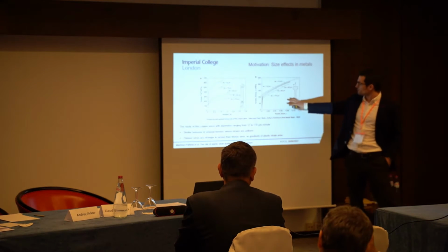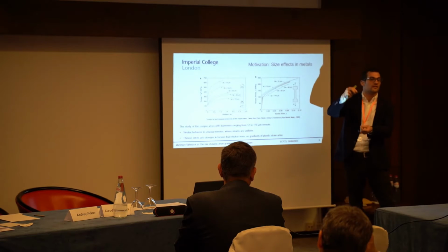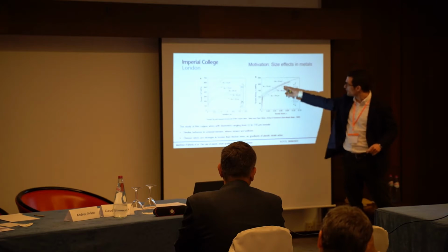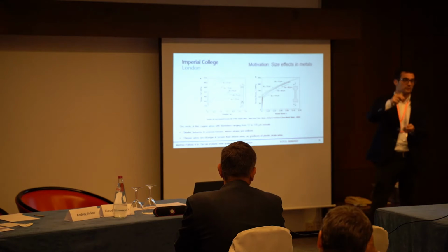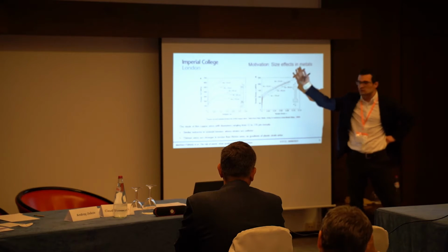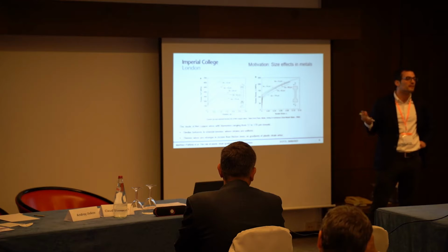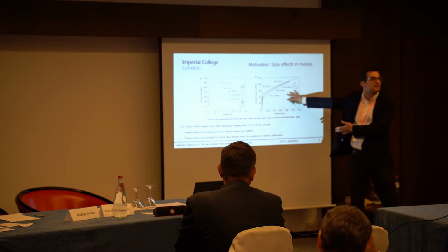Now what you see is that they tested the wires of different diameters, so different sizes of the wires, and you can see that in uniaxial tension, when you have uniform strains, the stress-strain curve that you get is more or less independent of the size of the wire, as you would hope and expect.